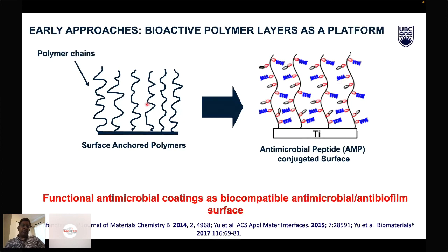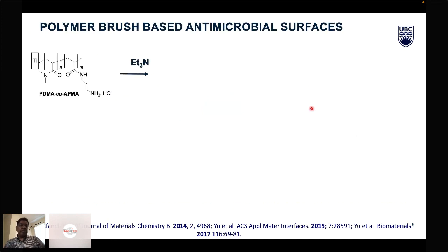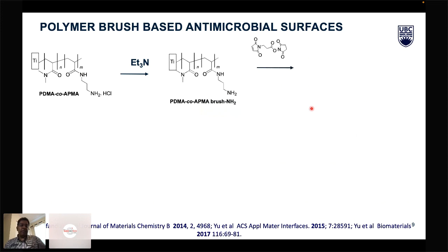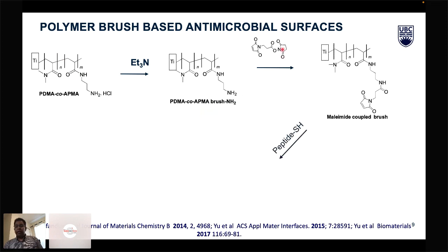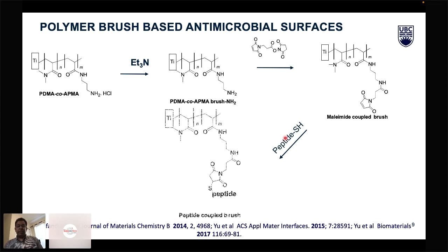So these polymer brushes provide anti-adhesive properties. And then if you attach the right type of antimicrobial agent, in this case we were using an antimicrobial peptide, the reason being that it has a multi-mode of action, and there is less chance of developing drug resistance. Using this concept, we started with an example using a titanium surface. We used surface initiated polymerization to generate a surface grafted polymer, and then we modified it with a peptide linking agent, and then utilized cysteine containing peptides to generate a peptide conjugated surface.